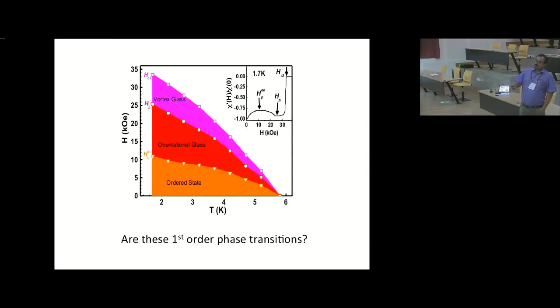So now what we ask ourselves is, if these are driven by pinning, are these at all phase transitions? Now, of course, BKT predicts two continuous phase transitions, but we know that this is not BKT. Regular melting is first order. So we ask ourselves whether these two could be two first order phase transitions to start with. And one of the signatures of a first order phase transition is that across the phase transition you should have superheating and supercooling. Now there are other signatures like latent heat, which are considered to be confirmatory signatures.